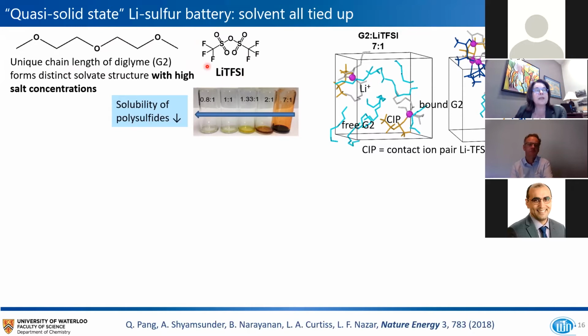And the point is that as it wraps around this pair, it prevents the diglyme from solubilizing the polysulfides. So at high electrolyte ratios, you can see the intensity of the solution from those dissolved polysulfides. But as you go to high salt and low electrolyte concentrations, there's almost no solubility of the polysulfides.